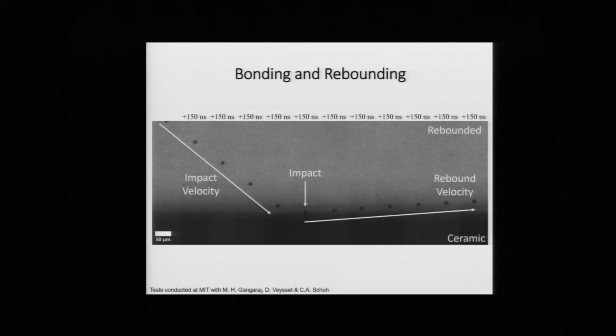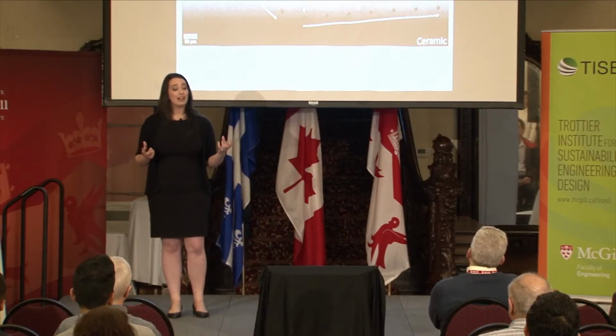And once this metallic particle passed in front of the high-speed camera, you could see when it will bond and when it won't. So in a case that it didn't bond, this is what the images would look like. Effectively, you can see that the particle is impacting at a relatively high velocity and then rebounds. And the rebound velocity is actually lower than the impact velocity. And in fact, if you take a ratio between the rebound velocity and the impact velocity, you get what we call a coefficient of restitution. And this is basically a measure of how much energy is lost during that impact. So it's a quantification of the amount of energy you're losing due to plastic deformation.